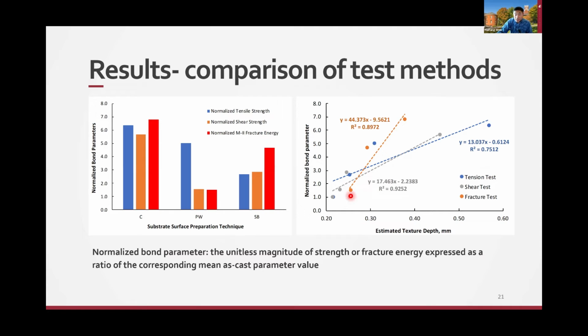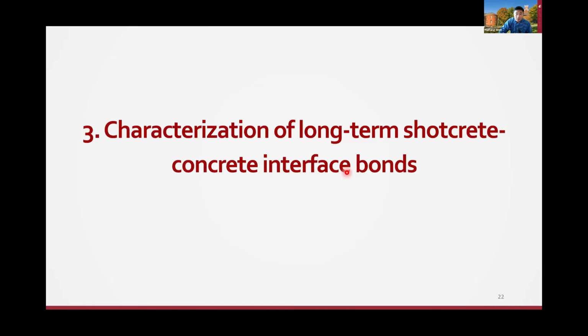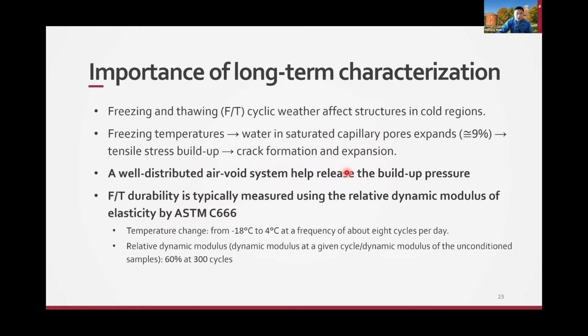From here, if you look at the standard, we probably look at somewhere here, that gives you enough shear strength. And then we look at the long-term durability of the interface bond, specifically the freeze-thaw method. Freeze-thaw can affect the bond or accelerate the bond failure because the water will be freezing and pushing the material away from each other. And that can also be related to the air void in the system.